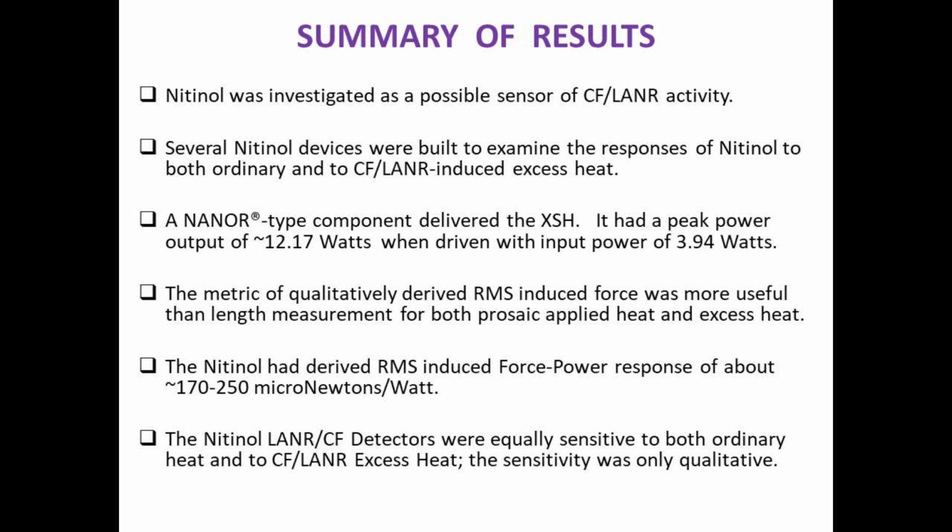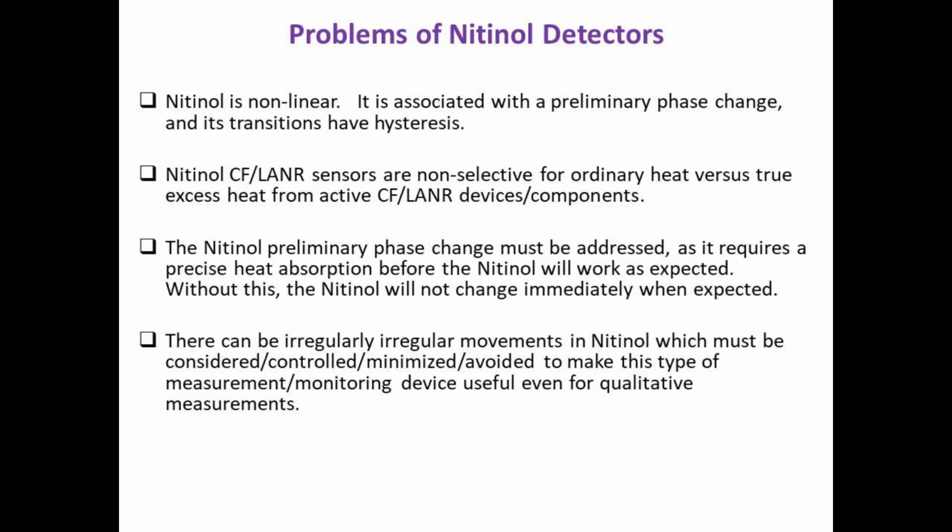However, the nitinol sensors were equally sensitive to both ordinary heat and to cold fusion excess heat. And worse, the sensitivity was only qualitative. The problems of nitinol detectors in cold fusion are that they are nonlinear and that they have a requisite preliminary phase change and that all of their transitions have a hysteresis.